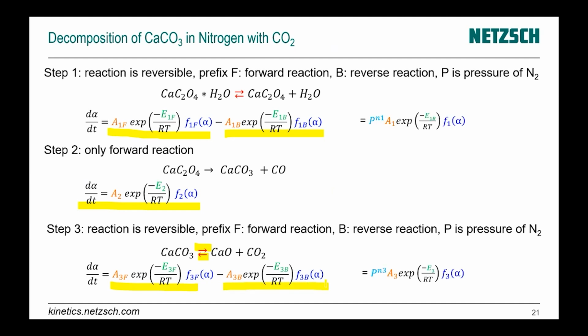And here, during our simulation or kinetic modeling, we can make it a little bit easier and just assume that the activation energy for the forward and reverse reactions is the same, and the reaction order is the same, and only the influence of the pre-exponential factors, they are proportional to the pressure to the power n, where n is our degree of the pressure, and P is the pressure of the pure nitrogen in this case. And the same for step number 3. Here, P is the pressure of pure nitrogen, and here we have an additional part.